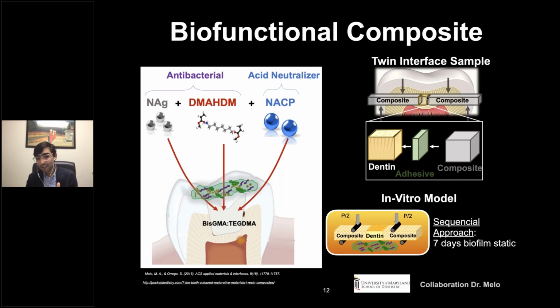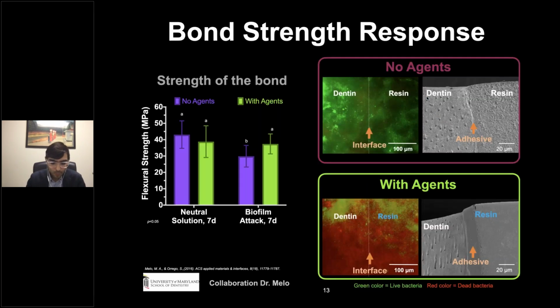After the 7 days, what we did was to assess how strong was the bond between these 2. This is what you see here in this left graph. In the y-axis, I'm showing the flexural strength of the bond strength. It's like when you glue 2 parts together, how much force you need to break that bond.